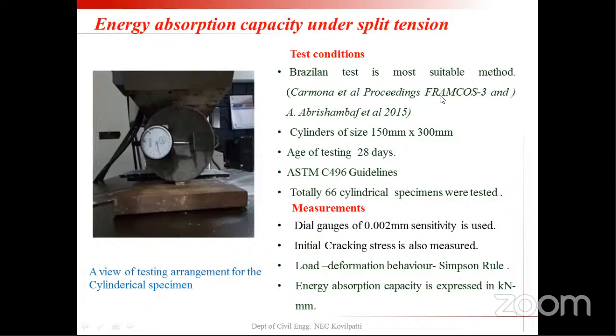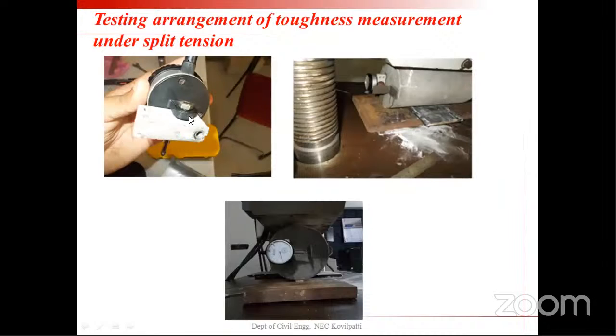I have conducted the Brazilian test as per the literature. This testing procedure is followed as per the literature given in the slide. It is conducted on the normal cylinder, and this type of special attachment has been made, and we used it to measure the deformation. I used dial gauges of 0.002 mm sensitivity. So from the load versus deformation observation, I measured the initial cracking stress, and I plotted the load deformation curve to measure the energy absorption capacity. And this is the arrangement of the split tension toughening test. I attached this dial gauge to the steel cylinder by means of this L-shape steel plate and with proper adhesives.